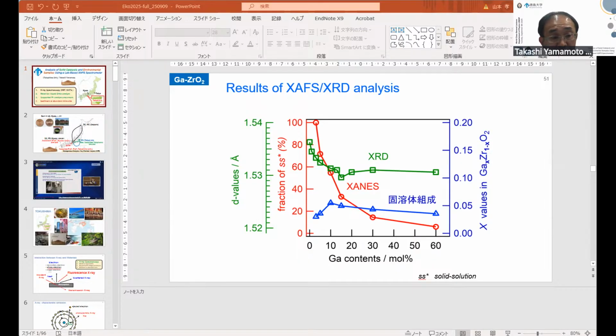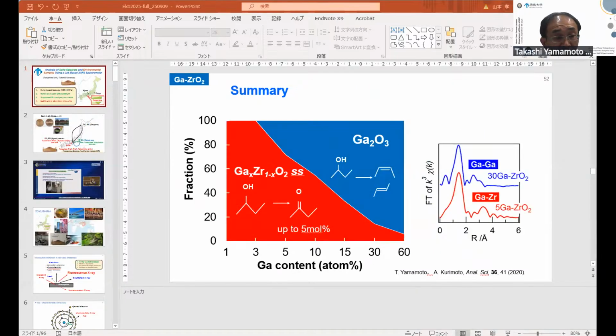Then this is the D values. The D values first decreased and then became constant. Then the position is almost identical. It agrees with the XAFS analysis and X-ray analysis. Then this is a summary of this catalyst.